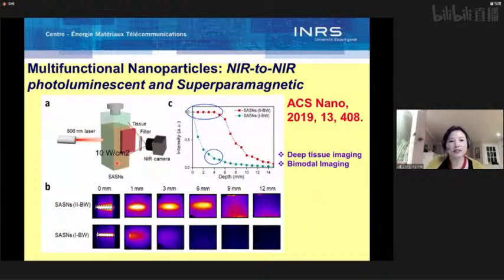And then we did near-infrared imaging studies. We use an 808 nanometer laser. We put our multifunctional nanoparticles in solution and put tissue here, and then use the camera to capture the signal. And here you can see that we can pick up a signal even at about 1 centimeter in depth.